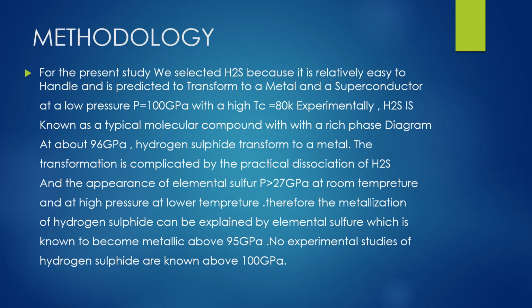Next, I present the methodology. For the present study, we selected H2S because it is relatively easy to handle and is predicted to transform to a metal and a superconductor at a low pressure, P equal to 100 gigapascal, with a high critical temperature of 80 Kelvin experimentally. H2S is known as a typical molecular compound with a rich phase diagram. At about 96 gigapascal, hydrogen sulfide transforms to a metal. The transformation is complicated by the partial dissociation of H2S and the appearance of elemental sulfur.